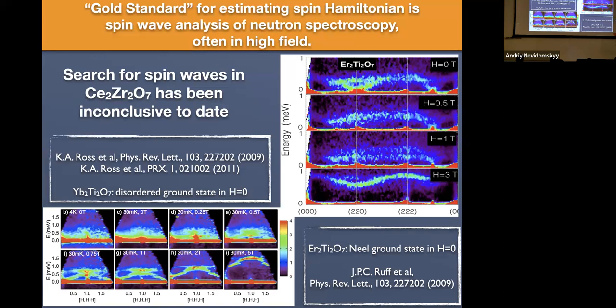Or you might start off with sharp spin waves, and you can get different sharp spin waves in the field. Anyway, that's the gold standard. That's what we would really like to do. But we can't see well-defined spin waves, either in zero field or in a field, in this material. And it's pretty much got to be because of the octupoles. We're not coupling strongly enough to the octupoles to see the equivalent of spin waves in such a system.